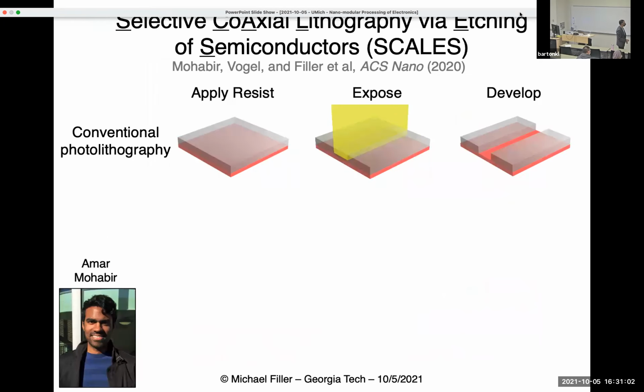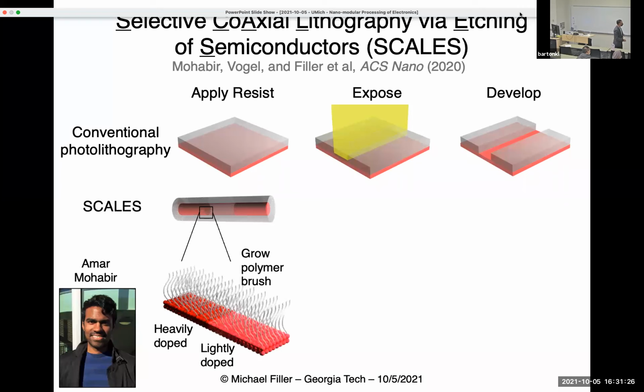So here we go. SCALES, the patterning step, is analogous but distinct from photolithography. So I hope most people who are listening know what photolithography is and how it works. Bottom line is you take a photosensitive resist, you spin it on a wafer, you expose certain regions with light, and those exposed regions, or the inverse, can be developed away to leave you a pattern. With SCALES, we leverage the underlying dopant profile. So we grow a wire, we put a polymer on the whole wire, and now it's grown as a brush, actually. So it's not spin coated, we just grow it off the surface, but it's still a resist.